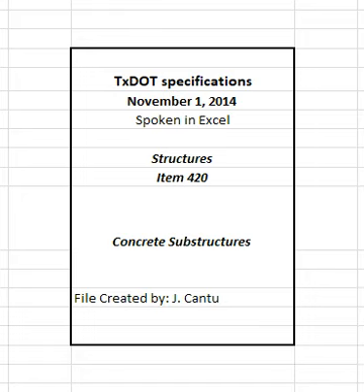Support tie beam or cap forms by false work on previously placed tie beams only if the tie beam concrete has attained a compressive strength of 2,500 psi and the member is properly supported to eliminate stresses not provided for in the design. Maintain curing as required until completion of the curing period. Place superstructure forms or false work on the substructure only if the substructure concrete has attained a compressive strength of 3,000 psi.